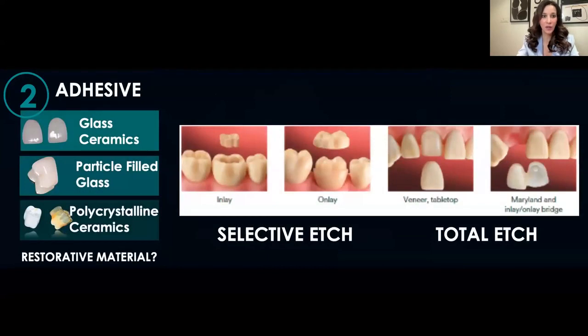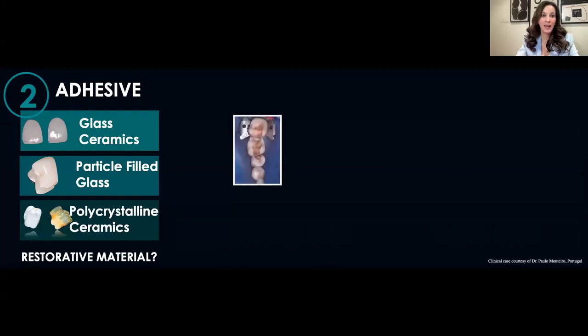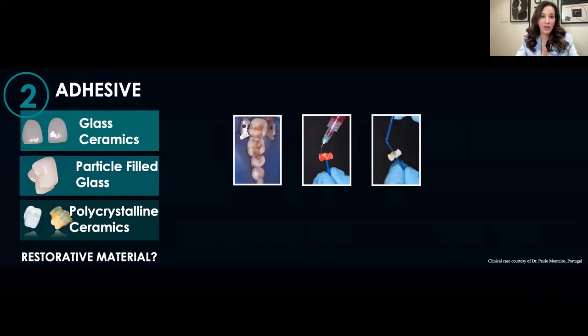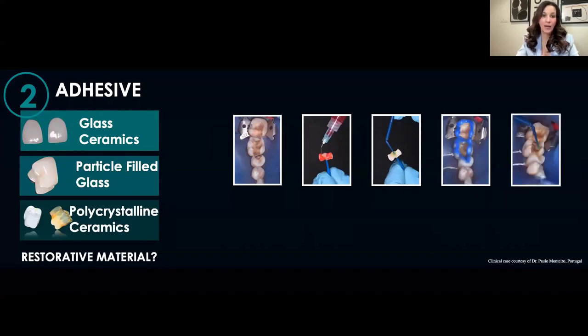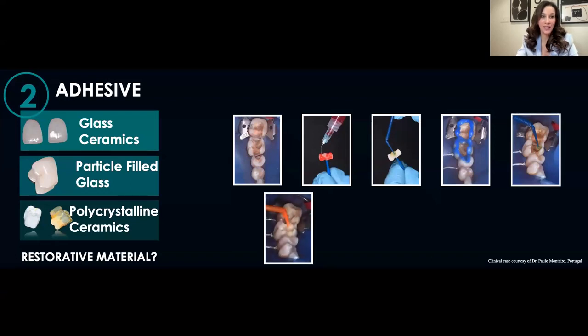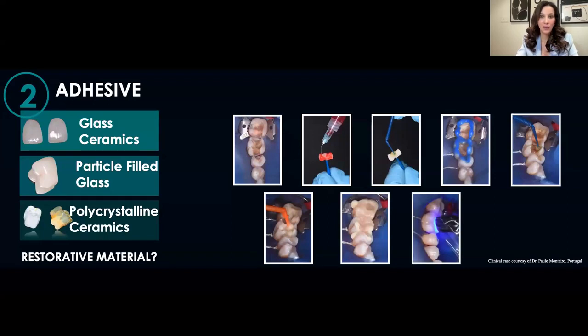For an adhesive protocol, that's when maybe you have a preparation design that's not quite so retentive. So you want to maximize the bond strength. The way you do that is you can use either a selective etch or total etch technique, and then you isolate the tooth. You etch the restoration itself. This is for the adhesive technique. Apply bonding agent to the restoration, etch the tooth, apply bonding agent to the tooth, and then you can use your self-adhesive cement and bond the restoration.